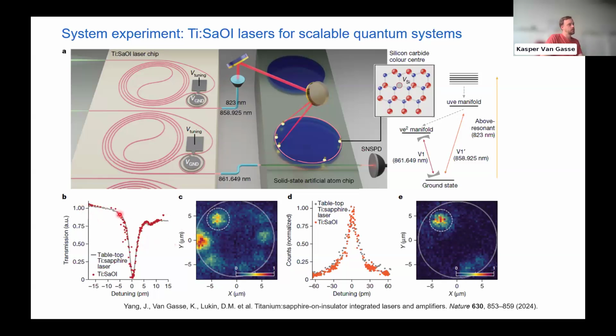And that's what you see here in these graphs. So this is, for example, resonator scanning, an important operation during this cavity QED experiment, where the gray line is what happens when you do it with a tabletop sapphire laser. And then with our tiny lasers, we achieve the red line. And this is without any packaging or whatever. This is just because of the quality of the platform. We can already, with our $30 laser, get very close to the performance of this tabletop laser.